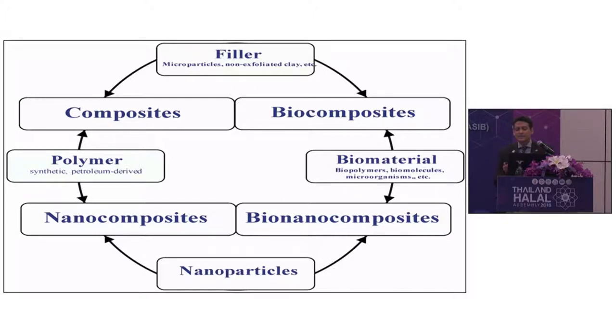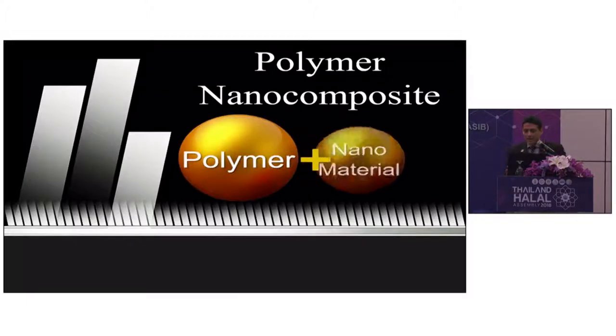This slide shows the terminology of composite and bio-nanocomposite. Why we call it composite material, bio-nanocomposite, or composites depends on the nature of the filler and the polymer matrix. If the filler is in micro particles and added to a biopolymer such as chitosan, it is called a composite material, biocomposite. If added to a synthetic polymer such as low-density polyethylene, polypropylene, or polystyrene, it is called a composite material. If the filler is in nanostructure or nanoparticles, added to a biopolymer it is called bio-nanocomposite, or to a synthetic polymer it is called polymer nanocomposites. So we have two phases.